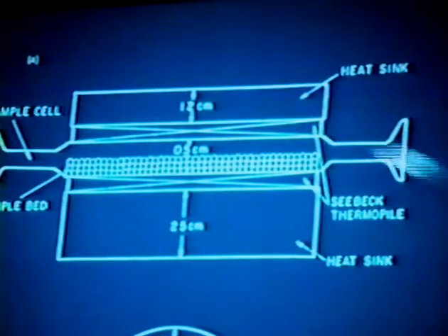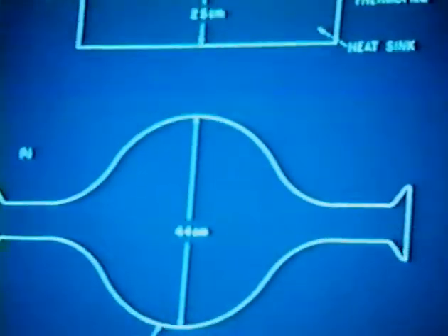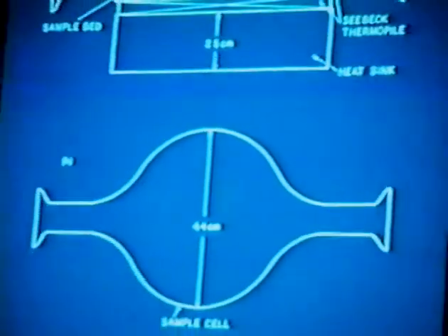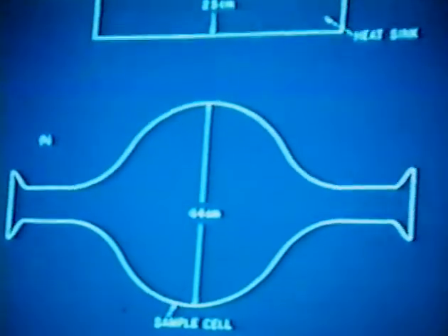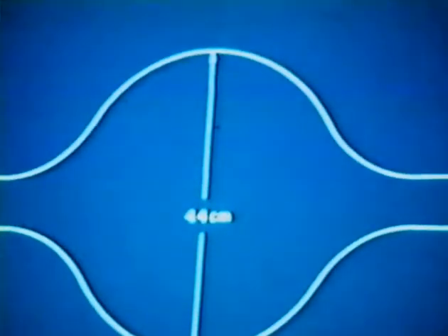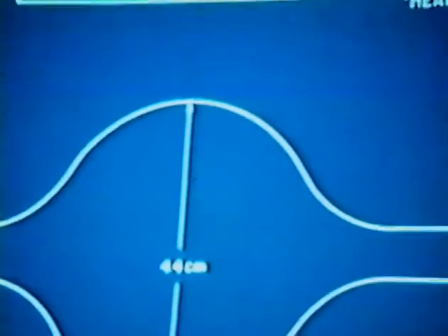Gas is admitted through one end, is absorbed in the bed, the heat is evolved and then is transferred through these thermopile sheets, and what we measure then is a heat flux as a voltage difference between what we see with this sample and a reference sample that's essentially a blank, an empty cell. And we can measure the actual amount of heat that's evolved and that passes through these thermopiles as the adsorption process and heat flow takes place.